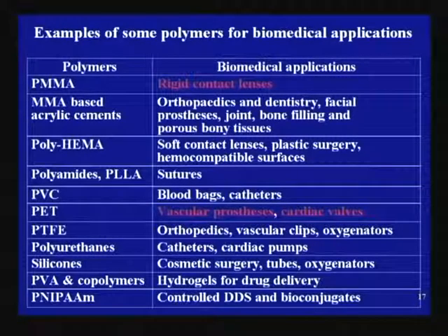PVC for blood bag. You have seen blood bag for collection of blood, that is made of PVC, although it is banned today. That is flexible PVC, plasticized PVC. It is banned globally, but in India nobody bothers. So, we are using this flexible plasticized PVC. The problem is it gives a life to the blood of only 30 days at 4 degrees Celsius. 30 days life is available.